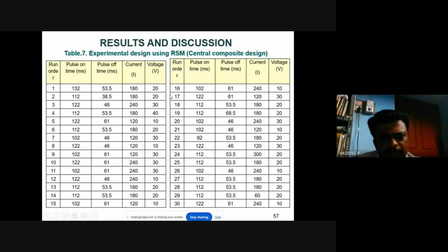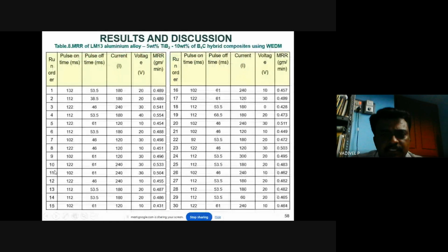So the experiment is done using the central composite design. The experimental design is done using RSM, response surface methodology, in which the central composite design is chosen. So here the run order is fixed from 1 to 30, with pulse on time, pulse off time, current and voltage. And this is the chart for 5 weight percentage of titanium diboride and 10 weight percentage of boron carbide using wire EDM. So these are the metal removal rates.